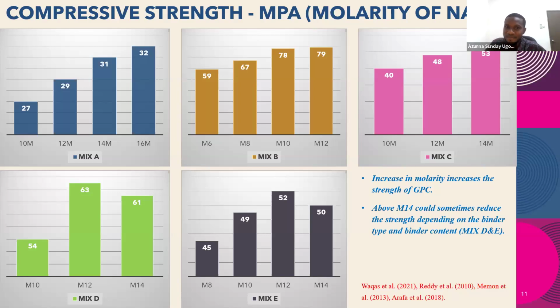the moment you add the alkaline liquids to your mix, because for geopolymer, normally you mix your fine aggregate, your coarse aggregate, and your binders, your alkaline precursors together first before you put the alkaline liquid. When you're producing geopolymer concrete, that is the procedure. So when your molarity is too high, you realize that the moment you add your alkaline liquid, in less than 5 minutes, your concrete has solidified. Solidified doesn't mean it has a good strength because it will have a lot of pores. You cannot compact it. So that is why you see in this situation, when you go too high, your strength is reduced, not because it didn't set very fast. It set actually too fast to the point that you couldn't compact it.